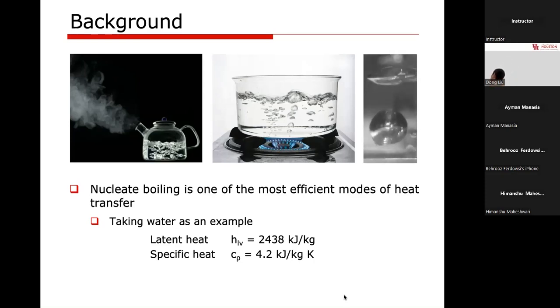Now, if you keep water as a liquid, and only rely on the so-called specific heat to absorb energy, you see the Cp is 4.2 kilojoule per kilogram per Kelvin. So that means if you have the same 1 kilogram of water, when you raise its temperature by 1 degree or 1 Kelvin, it can only absorb 4.2 kilojoule, right? So now you see there's a big difference if you use a so-called sensible heat versus the latent heat, right?